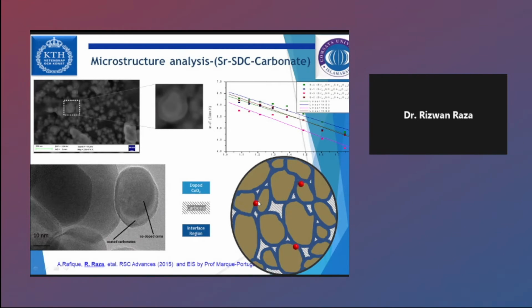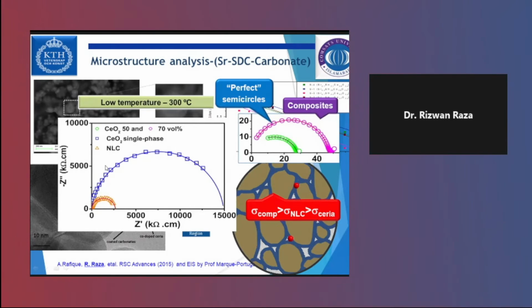Ions can pass through these interfaces, and its ionic conductivity is again increased from lower to high temperature. And we have prepared different compositions, and based on that, we have also studied some electrochemical impedance spectroscopy, and you can see a perfect semicircle, like an exact semicircle, which gives the confirmation for the ionic behavior of the material in the electrolyte. But here, you can see when there is a composite, its semicircle is more increased, resistivity is decreased and conductivity is also increased, and we published in different journals.